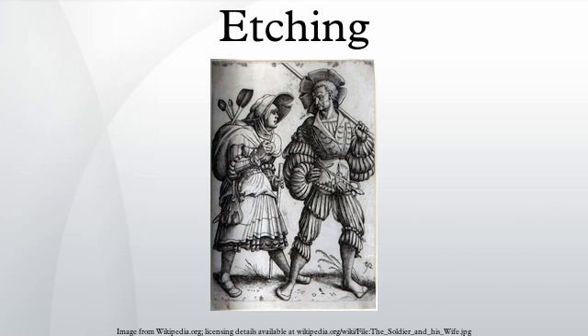A copper plate is good for, at most, a few hundred printings of a strongly etched image before the degradation is considered too great by the artist. At that point, the artist can manually restore the plate by re-etching it, essentially putting ground back on and retracing their lines. Alternatively, plates can be electroplated before printing with a harder metal to preserve the surface. Zinc is also used, because as a softer metal, etching times are shorter. However, that softness also leads to faster degradation of the image in the press.